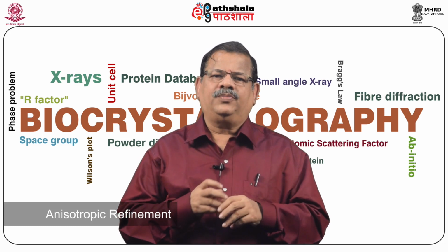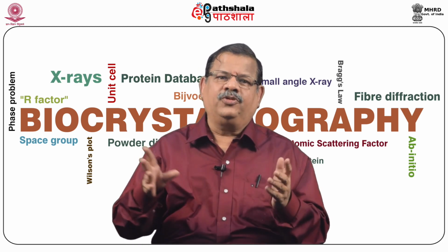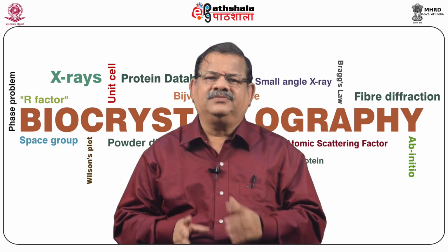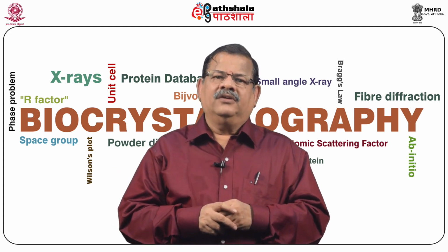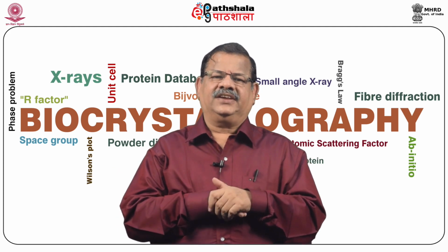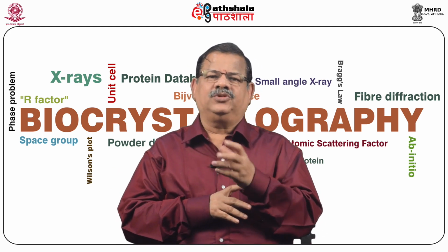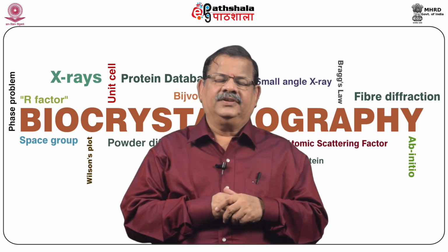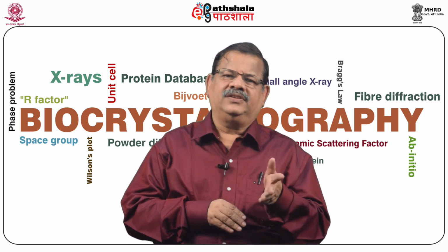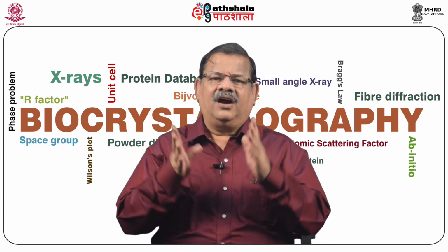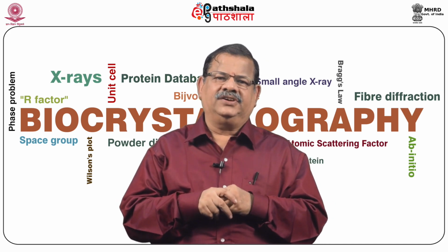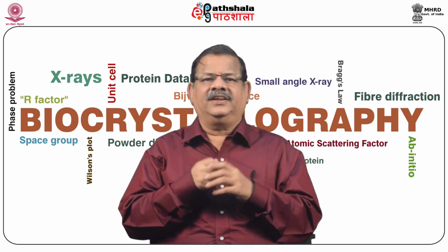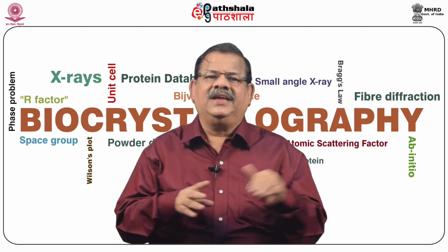Then anisotropic refinement will be started, with the output file renamed as the instruction file with the inclusion of the command ANIS, meaning anisotropic. Now we have the original X, Y, Z directions in which vibration will be assumed to be unequal, and also 3 more directions will be there: cross directions between XY, between YZ, between ZX axes. Totally, movement along 6 directions is considered. So your vibration picture will not be like a sphere as in iso, but in anisotropic it will be an ellipsoid.